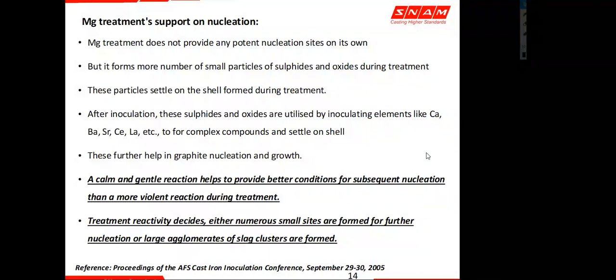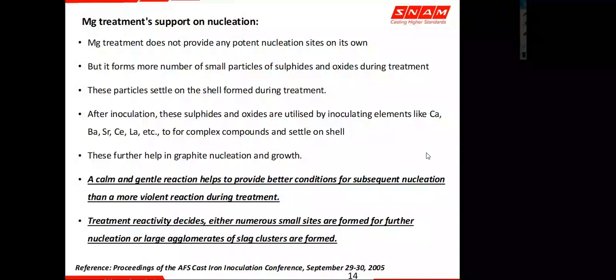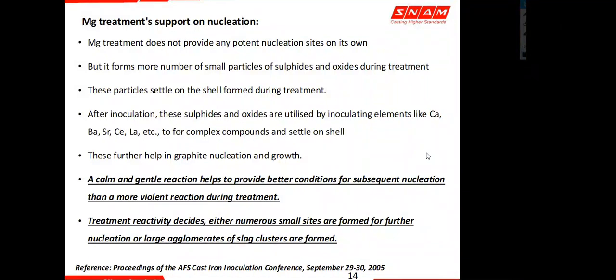After inoculation, these sulfides and oxides are utilized by the inoculating elements, which are added later, to form compounds which further settle on the shell formed during the treatment. This is how the nucleation happens, and then growth happens continuously.